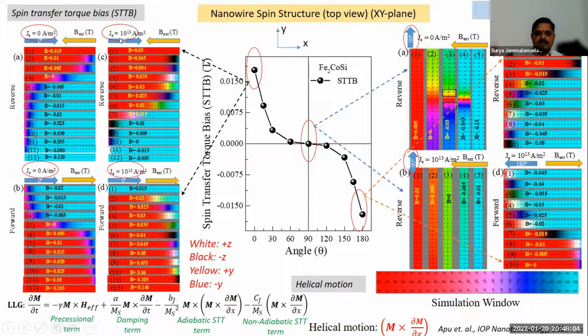Okay. So now when we try to send the spin polarized current, when you try to send the spin transfer torque bias through the magnetic nanowire, instead of moving smoothly, the domain wall is actually rotating its spin orientation in a helical fashion. So because of this, there will be a domain wall resistance that leads to the shift of the hysteresis loop along the magnetic field axis. Okay, so we attribute such kind of domain wall resistance could be due to the fourth term that exists in the Landau-Lifshitz-Gilbert equation, which is basically the non-adiabatic spin transfer torque term.